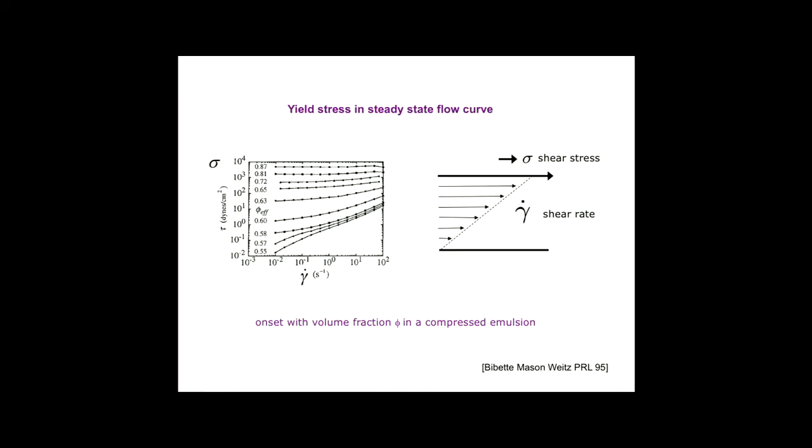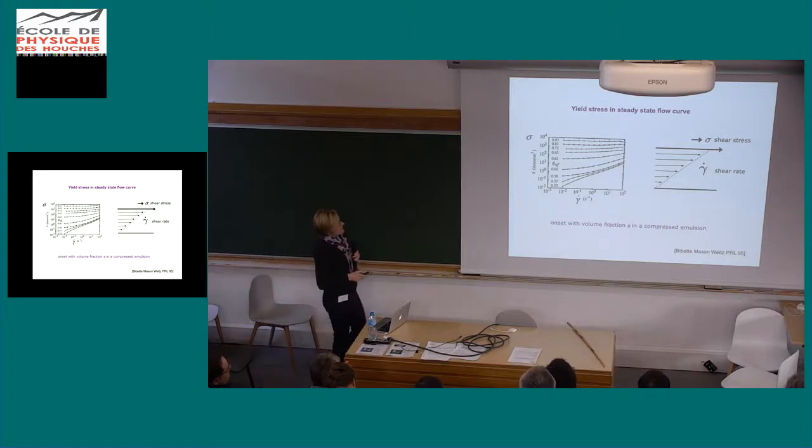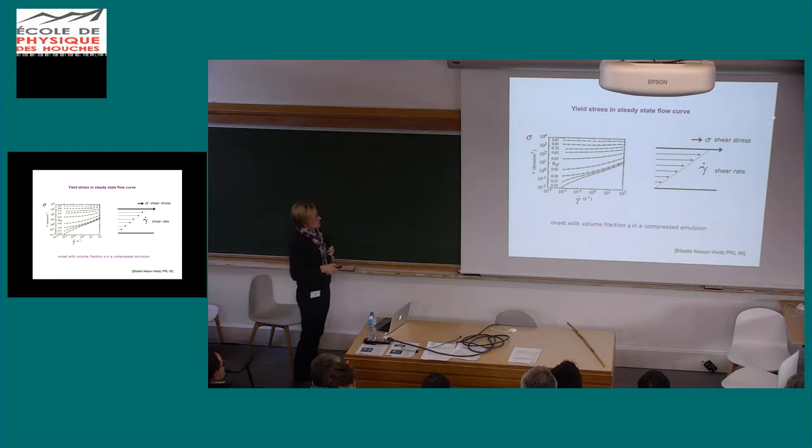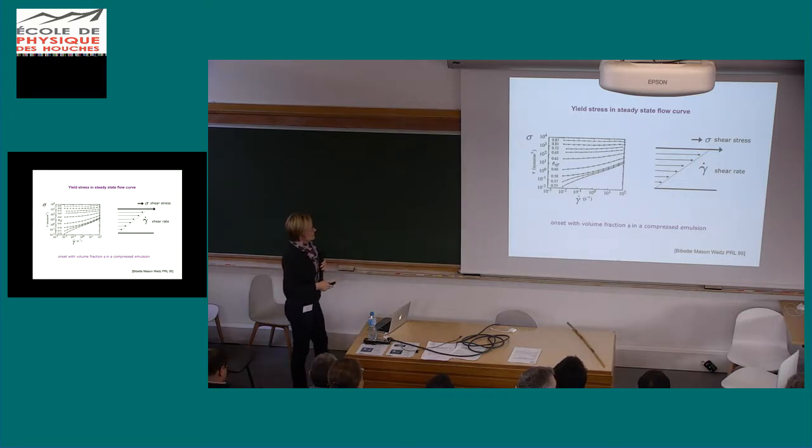And the most obvious feature that these materials have in their rheology is that in the steady state flow curve, so that's the relationship between the shear stress, the force per unit area at the wall, and the shear rate, that's the plate speed normalized by the gap size. So in a steady flowing state where nothing's changing as a function of time, then the most striking feature is that at a high packing fraction of the droplets, then as one extrapolates the shear rate to zero, one doesn't see the stress go to zero as one would in water, for example, but it extrapolates to a non-zero constant, and that's called the static yield stress.